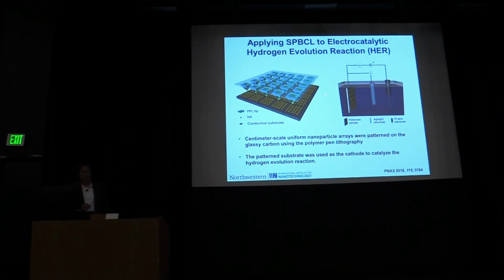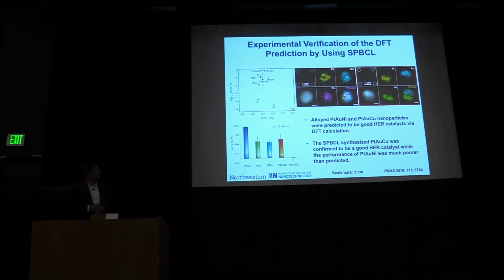So we can also pattern on electrodes, glassy carbon electrodes in this case, and we can build libraries of many of the same particles and look at the behavior of one particle at a time, but many times over. And so in this case, we're going to look at it in the context of the HER reaction, hydrogen evolution reaction. So we went to Chris Wolverton, a great theoretician at Northwestern, and asked, can you look at the different types of metal possibilities, structures that hadn't been made before, and tell us what might be good in terms of the HER reaction? And then we can synthesize in a nanoscale form. We can only do it in bulk scale form, but we can synthesize in nanoscale form and see if they actually map or where they deviate.